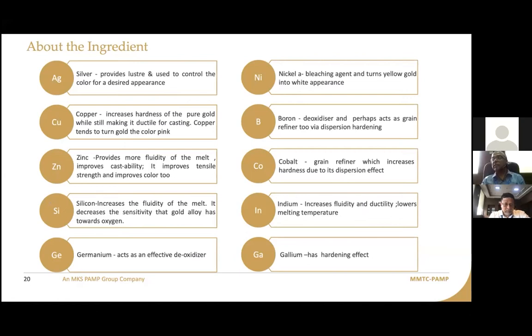Now, silicon and zinc work in a synergistic way. That means they work in combination, and this helps to get less oxygen absorption in the metal, and at the same time it reduces the surface tension. As a result, the interface reaction between the mold investment surface and the cast surface is reduced, which helps to improve the roughness. That means reduced roughness, reduced gas porosity due to sulfur dioxide liberation from the investment powder, and also a better shine on the surface, which has an effect on polishing and on the gold loss in the pre-polishing stage.